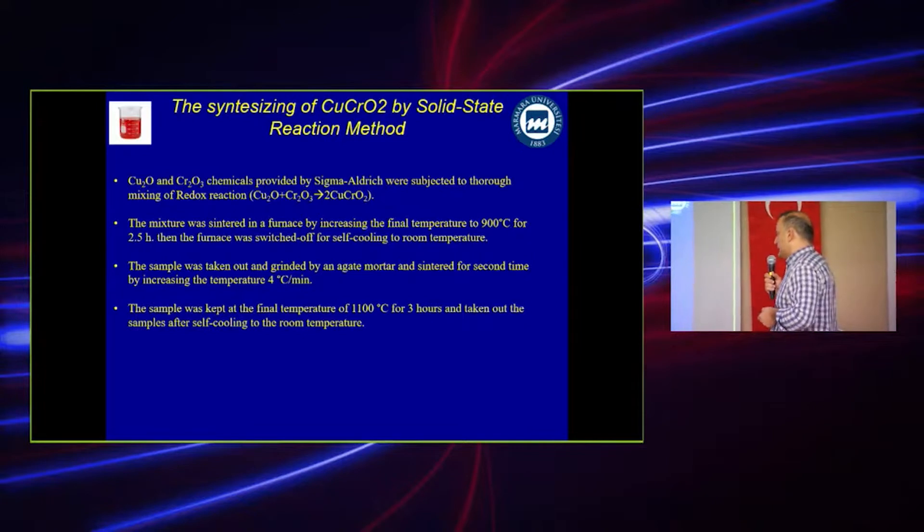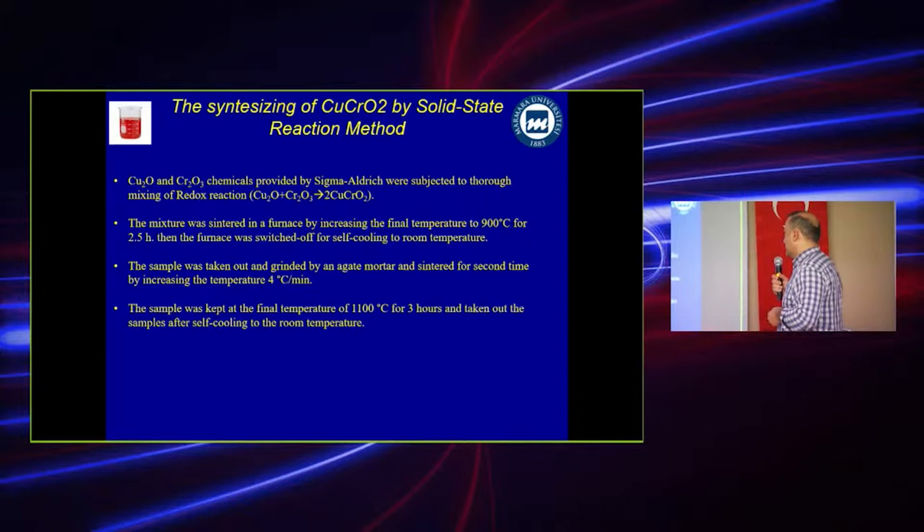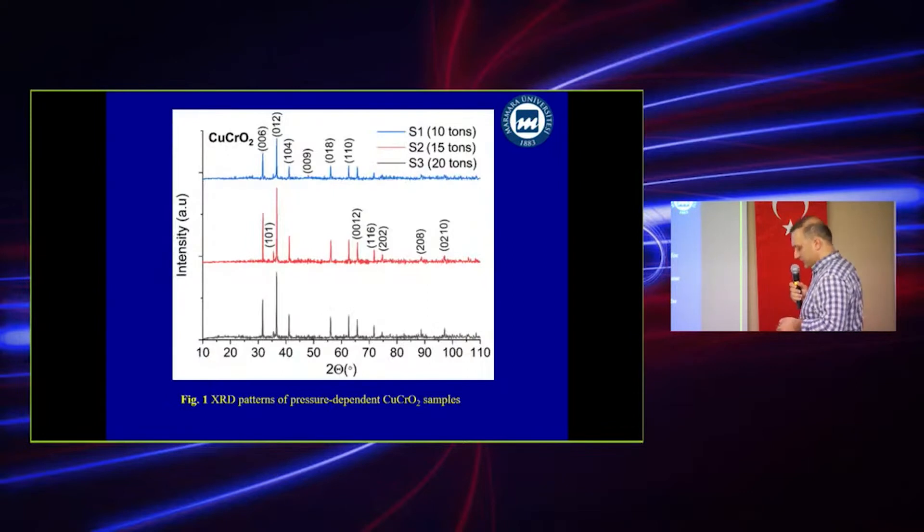The sample was taken at the final temperature of 1100 degrees Celsius for three hours and taken out for self-cooling to room temperature. This is actually what we did. This kind of samples are sensitive to temperature and pressure.